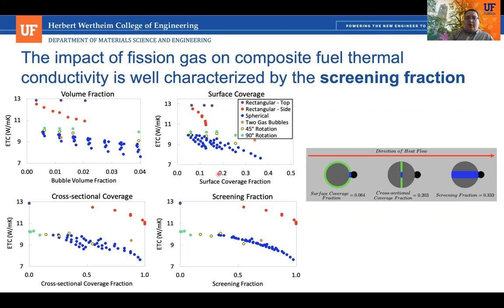There's a big spread. When we look at the surface coverage fraction, which is the overall fraction of the surface area that's covered by the bubble, we again don't see any clear correlation. Now, if we look at the cross-sectional coverage fraction, which is the fraction of the cross-sectional area of the high thermal conductivity particle that's blocked by the fission gas bubble, now we start to see these various dots start to collapse on top of each other. And then if we go to the screening fraction, which is the fraction of the total volume of the particle that's been blocked by the fission gas bubble, then they line up on each other very nicely. And then we're only distinguished now by whether we have a spherical particle or a rectangular particle.